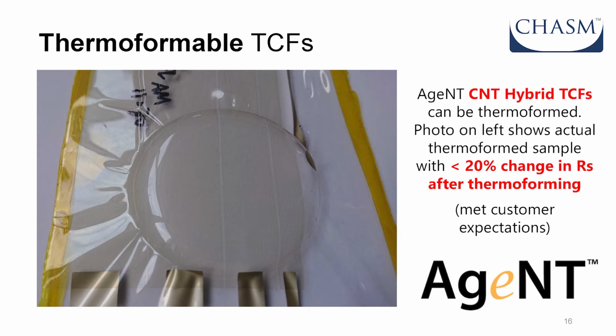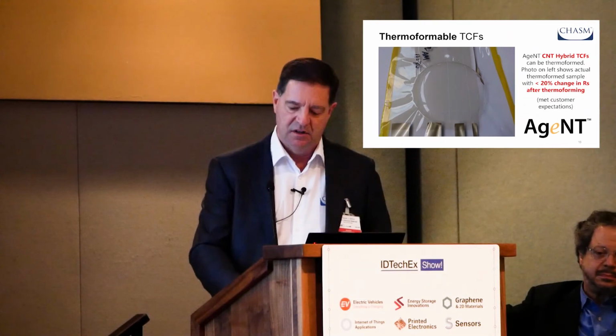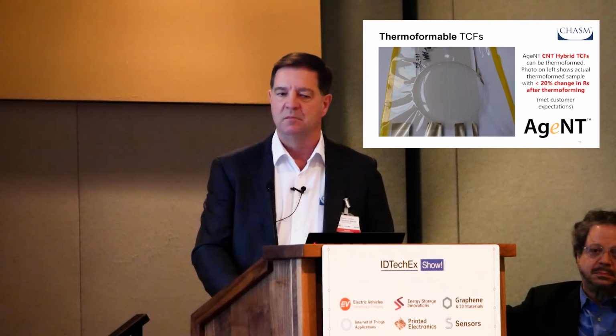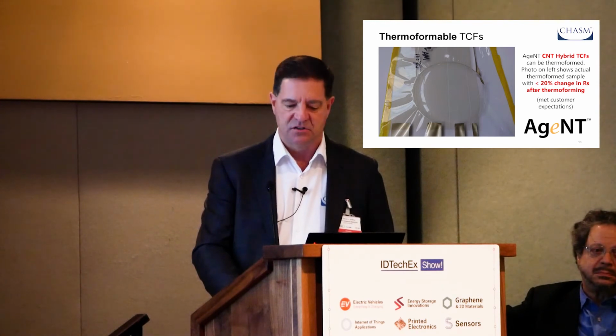We have done some work. We expect to do a lot more work with collaboration partners, but we have observed in thermoforming less than 20% change in the sheet resistance resulting from thermoforming. A lot of that percentage change is attributable to dimensional change, not material property change. And this particular example met our customers' expectations. So the ability to thermoform, the ability to have affordable processing, the ability to tailor the structure of the transparent conductive film, those are big competitive advantages of the AgeNT technology.